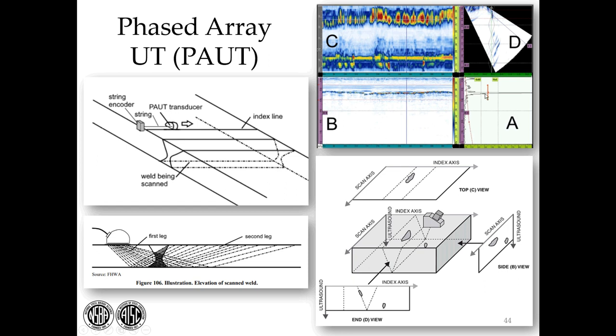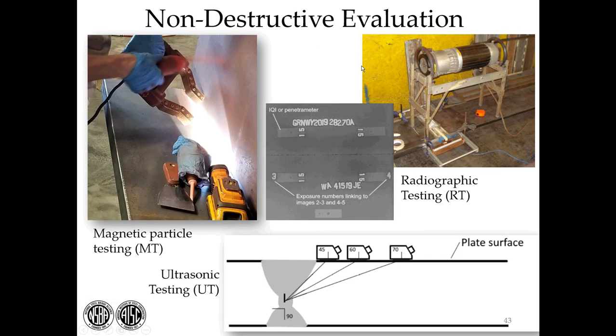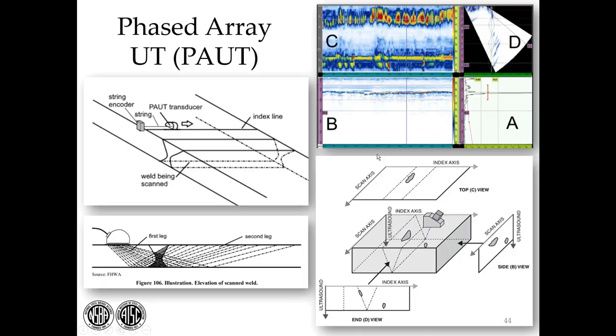So under the code, the allowance for pass-fail is based on whether or not you're beyond this gate. So here you see, this weld at this location does not pass. And actually, as you can see, all the way along the width of the weld, you see this defect. This happens to be the same joint that we saw in this previous picture with the RT, where you had a defect that goes the full length of the weld.